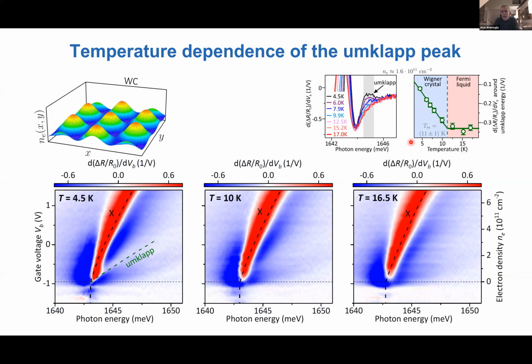So the reason I'm rather tentative is that, can we say something about this transition, where exactly it happens, or what is there in this transition region? With this kind of accuracy, with this kind of Umklapp strength, we cannot say much more. So I would say one can, in principle, study this, but we would need a much better sample where we also suppress possibly the radiative broadening, but most importantly, disorder broadening. And then we could get cleaner Umklapp signatures.